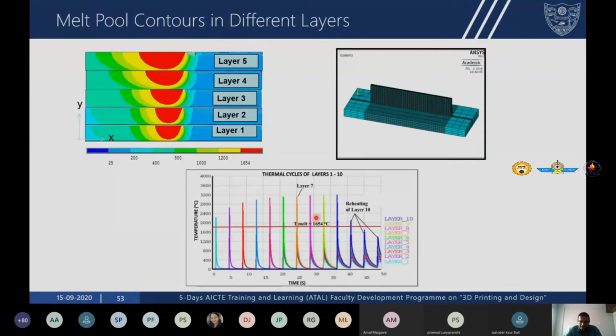Now this graph here shows the temperature cycling. As I told you, when you're depositing layer number 5, layers 1, 2, 3, 4 are heated and cooled. So this graph shows the heating and cooling cycles. I'll focus on the last 4 peaks. This blue peak shows the temperature when layer number 10 is being deposited. So when layer number 10 is being deposited, this is the temperature profile. Now this is the temperature profile in layer number 10 when layer number 11 is being deposited.